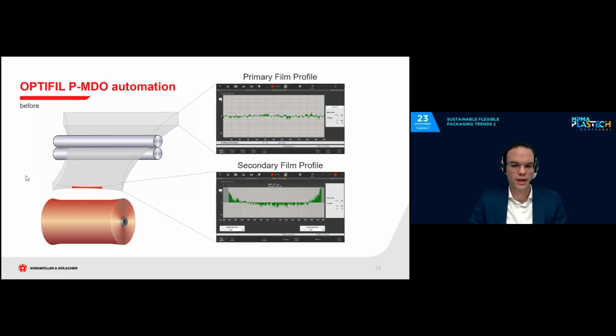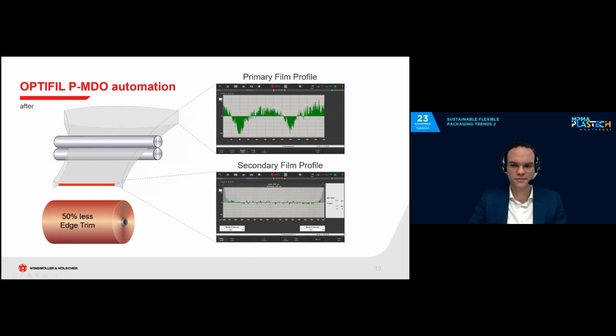Here is where PMDO comes into play. And now you see the film profiles with MDO automation on. We alter the primary film profile with the heating cartridges and bearing in a way that counteracts the edge buildup after stretching. What I mean by that, we create two thin spots in the bubble exactly where the film edges will be in the MDO process. And of course, we have a reversing haul off. That means the two thin spots need to travel with the reversing of the haul off.